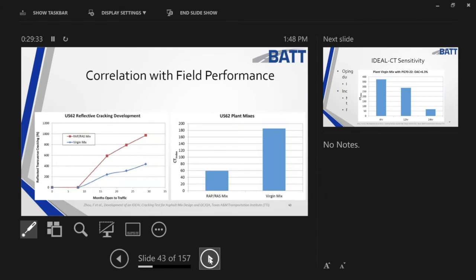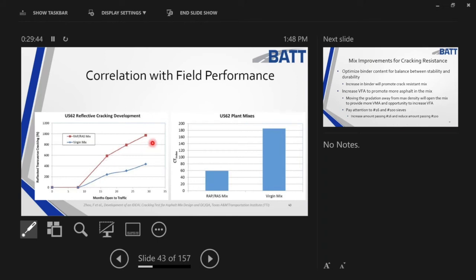Last slide on how we began to correlate and begin to look at how it performs in the field. What you're looking at on the left is cracking on the left axis, and then on the bottom is months open to traffic. The red one represents a RAP/RAS mix in Texas. Again, this is from Zhou and company down there at A&M. And then the bottom line over there represented just a virgin mix, or one that had no wrap or RAS in it. So it naturally had better cracking or less cracking. Look at the RAP/RAS mix over here on the ideal CT, and then look at the virgin mix. Look at the difference in the two. So real life, we can predict it in a laboratory, and that's just one data point.